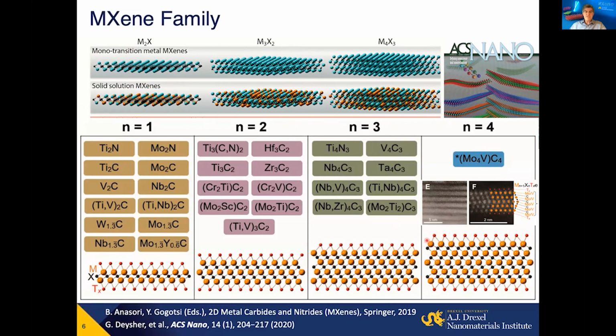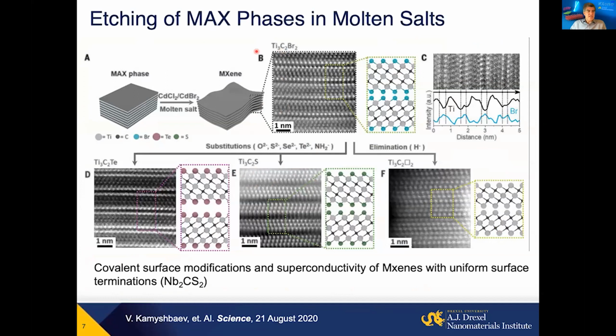We have the surface termination at the end. Usually we have oxygen, OH, some fluorine when we do etching in aqueous acidic solution. But when you use molten salt, for example, chlorides and bromides, the method developed in Ningbo initially and further pushed by Dmitry Talapin's group from University of Chicago in this paper published in Science about a month ago, it's possible to make bromine or chlorine terminated MXenes. And bromine or chlorine can be replaced with oxygen, sulfur, selenium, tellurium, amino groups, or surface termination can be removed, making basically non-terminated, electride-type structure MXene. So we have another level of control of chemistries of materials.